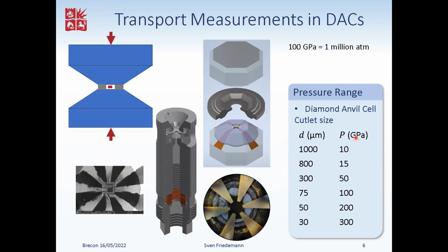I've already essentially said what pressures we can achieve, but here again is an overview of what that dictates in terms of sample size. If the culet is say a millimeter in diameter, that means of course the sample space can only be half of this, because the hole in the gasket is roughly half the diameter of the culet itself. So for 10 GPa with a culet of 1 millimeter, we've got a sample space that's about 500 micrometers, and that corresponds to the hole that's visible here in this picture.